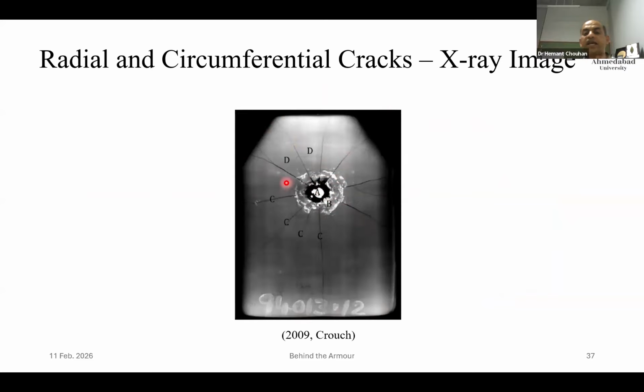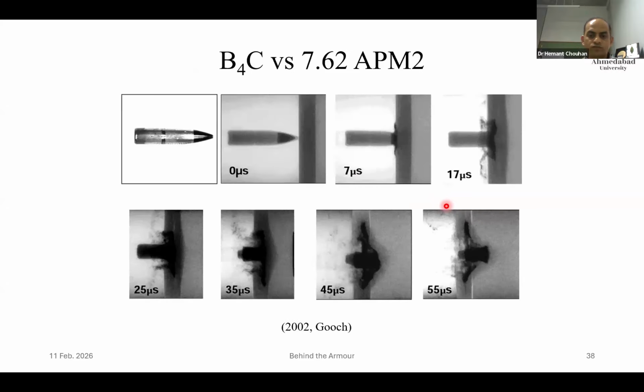So we see that if I take a second shot and by mistake it happens to hit on this, let's say this character C, which is a crack location, then this second bullet is bound to penetrate this panel comfortably. So that led to the decision that monolithic tiles are only applicable when we are firing only one bullet or at the max 2 to 3 bullets. But if we are going to fire 6 to 8 rounds, then these kind of radial and circumferential cracks will make the life miserable for the composite designer or for the bulletproof panel designer.